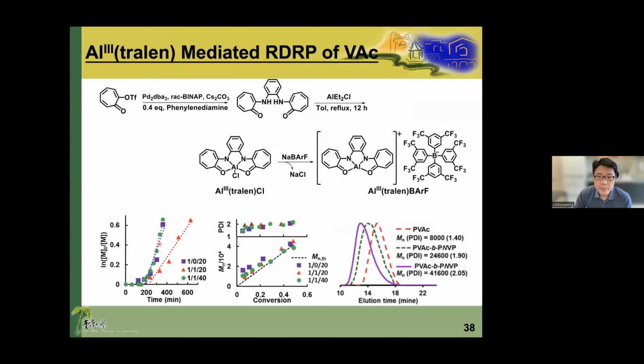So with the collaboration with Professor Chen Changle in China, actually he designed this special ligand. It is also a 2 oxygen, 2 nitrogen ligand, but with different substituent. So we use this ligand to coordinate with aluminum, and then use this salt to remove the chloride of aluminum and form this active species. And using this active species, we found it can control the vinyl acetate polymerization just like cobalt. So you can see an induction period and polymerization. The molecular weight increases linearly with conversion, and in GPC traces it moves smoothly.